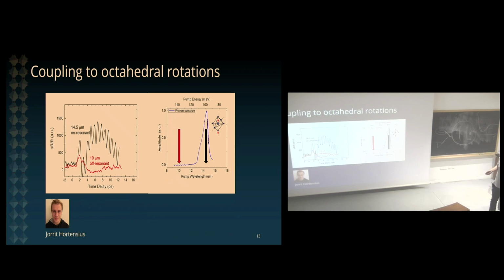And this was emphasized by the experiments of Jorrit, who has now finished his PhD and is working in industry. So what Jorrit has done in this experiment is taking a crystal of lanthanum aluminate, exciting it with one of these laser pulses, and then interrogating the lattice dynamics by looking at changes in reflectivity of an 800 or 400 nanometer laser beam. Okay, and what he sees is that if he's exciting the system off resonance with a 10 microns wavelength pump pulse, he sees a very incoherent and rapid decay of the signal.